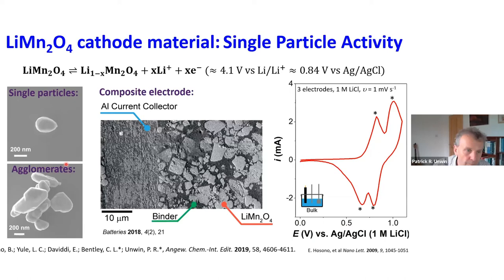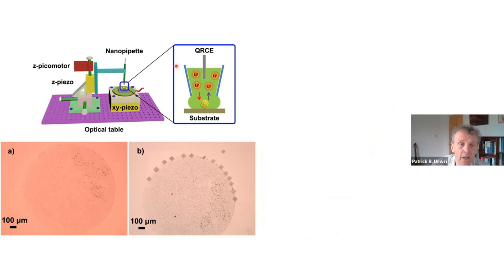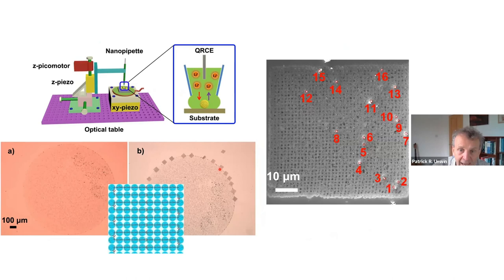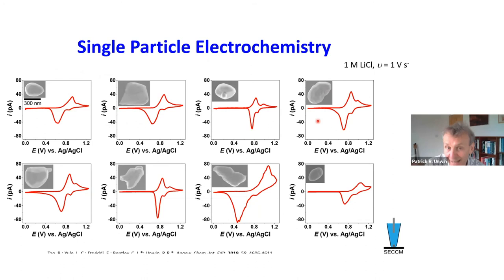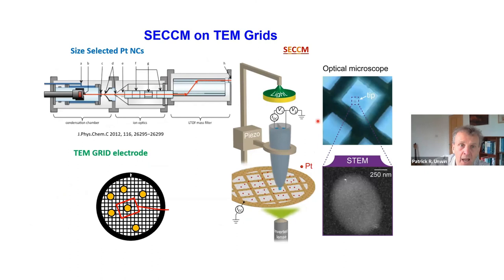I think this is going to be a great technique for battery electrodes. We've started looking at lithium manganese oxide cathode material, examining single particle activity. This is data from Bing Lin Tao — a lot of very successful scans during just a few days of experiments. You can go in with SEM afterwards, look at where you did those measurements, and fish out the local electrochemical properties of particular particles. Different particles sitting on a conducting support have very different electrochemical properties, which is very important for designing battery electrode architectures.